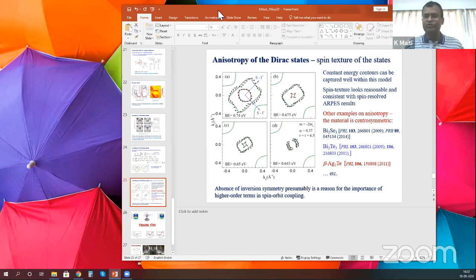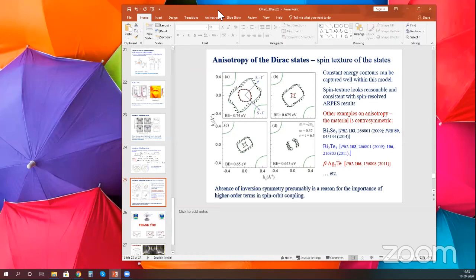Experimentally, you get the true Brillouin zone mapping. If there is a zone folding, experimentally, you'll be able to find out from ARPES. Normally, for example, if you have density waves, these are good examples like SDW, CDW, and so on, or antiferromagnetic ordering. Wherever there is a zone folding because of additional symmetry, you often see the bands folding back, there is an opening of gap that you can exactly find out from experiment. So here, experimentally, we find that actually the Dirac node that was wrongly identified at gamma point is not at gamma point, but at the S point. From calculation, it was found at gamma because they used a bigger unit cell for their calculation. The moment you use a bigger unit cell, your effective Brillouin zone becomes smaller. So that gives you zone folding.